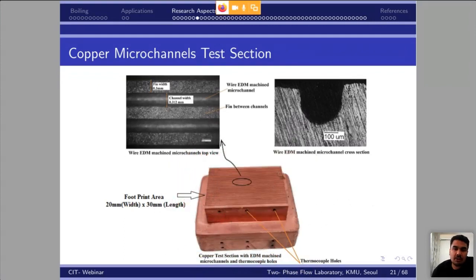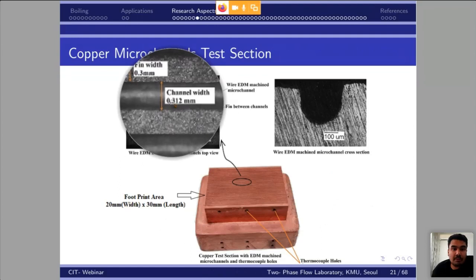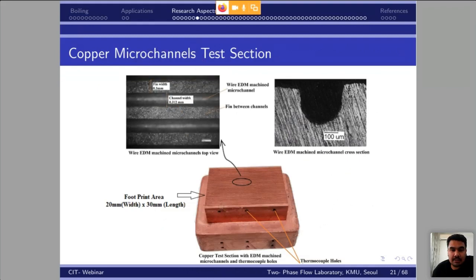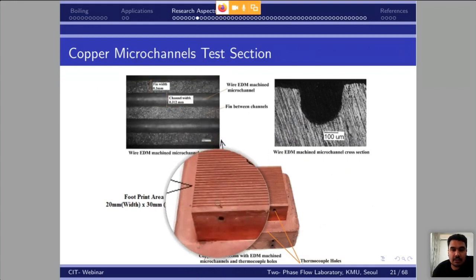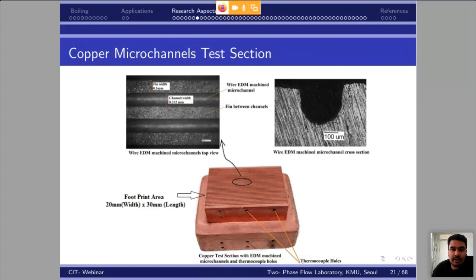We are mainly concentrating our talk on these small size channels, not on big size channels, because the big size channels have already been explored much. So it is better to have a look at what is happening inside small channels during this flow boiling. These are the channels with 0.3 mm diameter, that is 300 microns, nearly 300 microns diameter. This is the heat sink with 31 parallel channels you can see here. This is the testing block actually. We can heat the block and allow the fluid to pass through and test the performance.